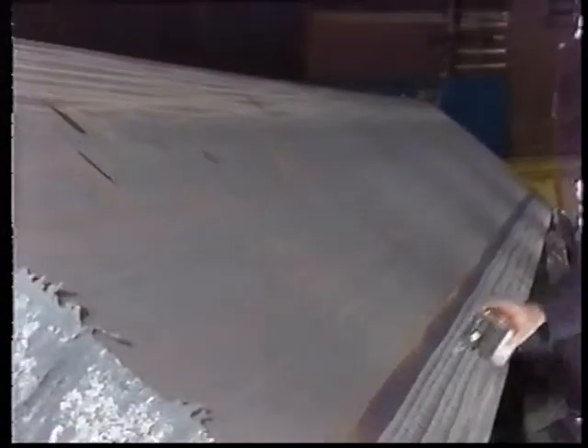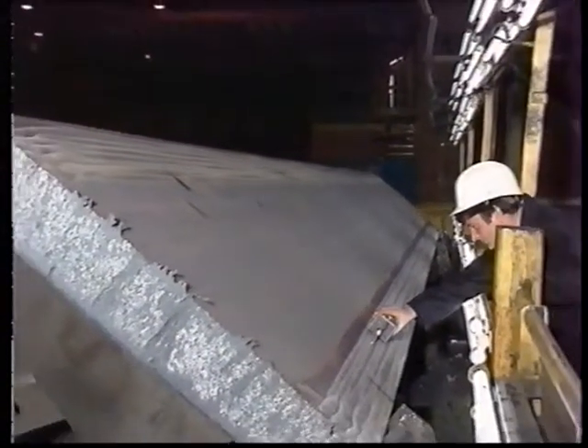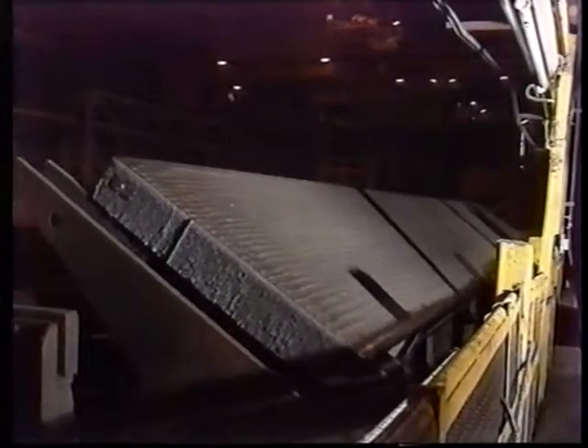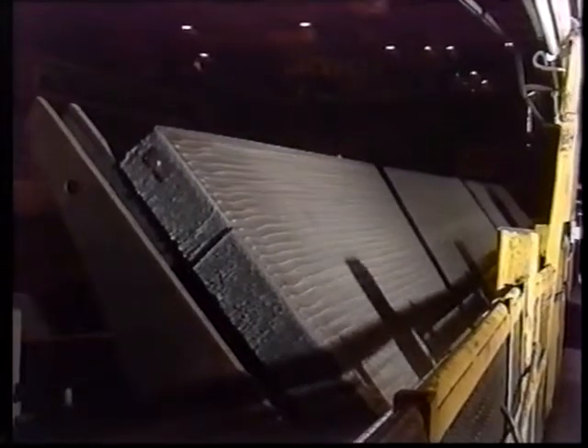In the slab processing bay, the cooled slabs are inspected prior to grinding. The extent of the grinding required may vary from full surface preparation to intermittent spot grinding, depending on the condition of the slab surface. Grinding the defects out, this is a tramline grind, one of the many types of grinding that we do down here. It's ground down the edges and we have to provide a surface finish that falls within the standards. When grinding is complete, each slab is tilted under high-intensity light for a final rigorous inspection and surface roughness check.